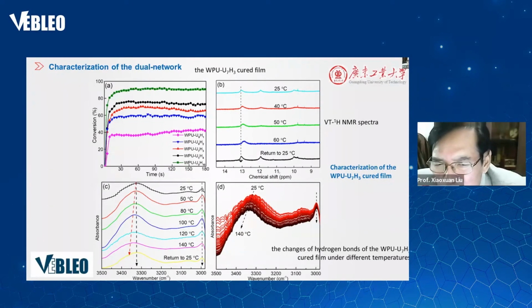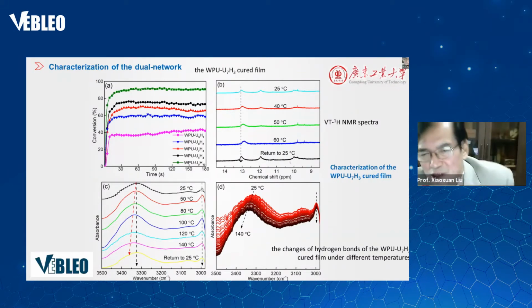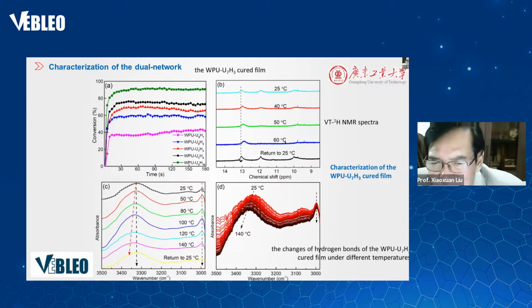This is the NMR spectrum at different temperatures. When the temperature goes from room temperature up to 60 degrees centigrade, the peak changes. So these are the changes of the hydrogen bonds of the WPU at different temperatures.